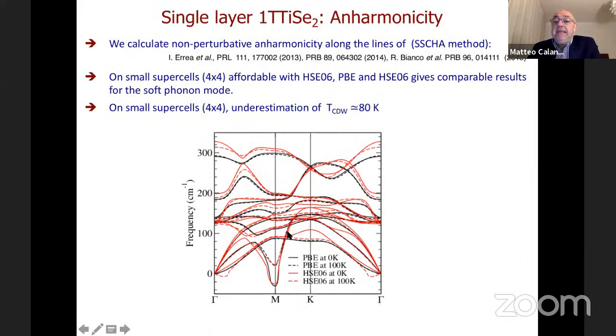This can be done with the techniques that we have developed in recent years, which you can see in these three papers. I will not explain the techniques in detail because it would take a complete talk only for that. But it involves doing many calculations, of the order of 1,000, on supercells with suitably chosen randomly displaced ionic coordinates. With this, you can access directly the quantum anharmonic free energy, and also the anharmonic phonons. Of course, you have to converge on the size of the supercell.